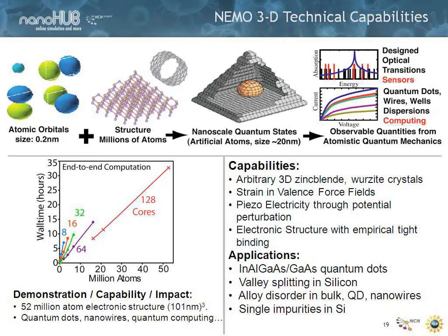So let me start with the downfalls of tight binding, the way we do it. We guess the structure, right? We guess how the atoms are connected and who is connected to whom, and then we do a valence force field relaxation to minimize the total strain energy in the system. So the guys can move around, but they can't change order and say, I'm going over here and you come over to my place, and therefore we minimize the total energy, right?